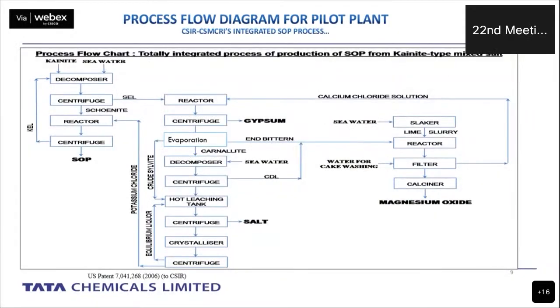The mother liquor coming out from the potassium chloride recovery process contains a lot of magnesium chloride, which is of good quality. So it is used for producing magnesium oxide, using lime to convert magnesium chloride into magnesium hydroxide, and it is filtered and then calcined.